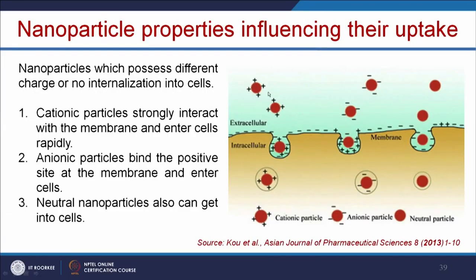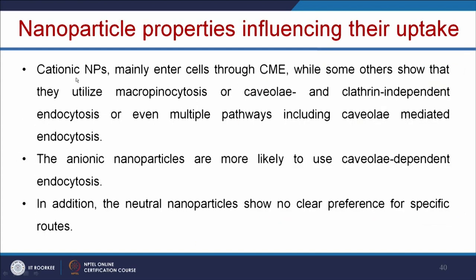So these cationic nanoparticles strongly interact with the membrane and enter the cells rapidly, and these anionic particles bind the positive site at the membrane and enter the cells. And again, neutral nanoparticles can also enter into the cells through various processes. Here these cationic nanoparticles mainly enter the cells through CME, and some research shows that they can utilize macropinocytosis or caveolar and clathrin independent endocytosis, or even follow multiple pathways including caveolar mediated endocytosis. And mainly the anionic nanoparticles are likely to be taken up by caveolar dependent endocytosis. And again, for the neutral nanoparticles, there is no clear preference for specific routes.